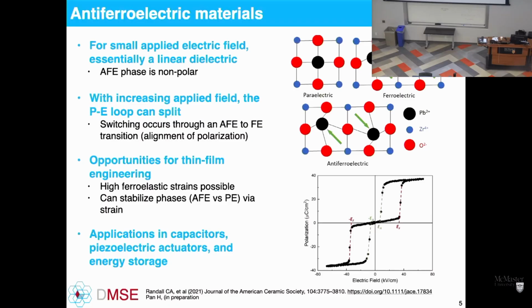Well, you're going to have rotation of half of those, or really all of the polarization, to try and line up along the direction of the field. And as a consequence, you can change the unit cell itself, meaning you can go from an antiferroelectric, and if you apply a strong enough field, all those dipoles point in the same direction, it becomes a ferroelectric.